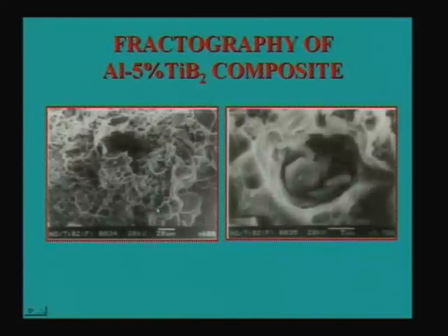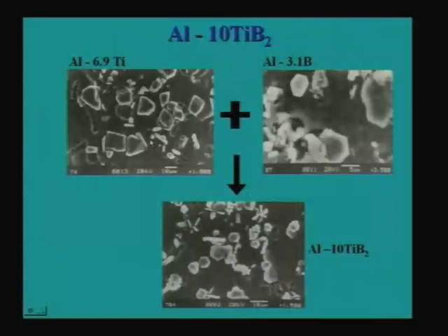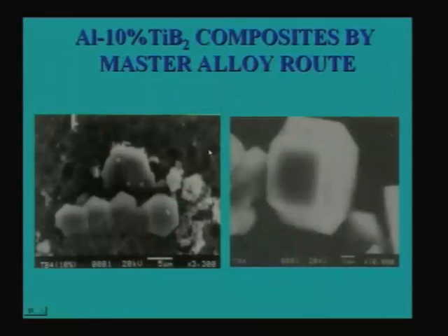So this is the fractography to show that these are all ductile fracture. That means though the strength is very high, still they are ductile. And this is for 10% TiB2, similar thing one can do. If you carefully observe the composition of titanium here and boron here, it is 6.9 and 3.1, and the ratio is 2.2 is to 1, and that is what we maintain. If you do not maintain this ratio, you will not end up with only TiB2, because ultimately in the composite you want only TiB2 particles. So one has to control this composition, and this is the morphology.